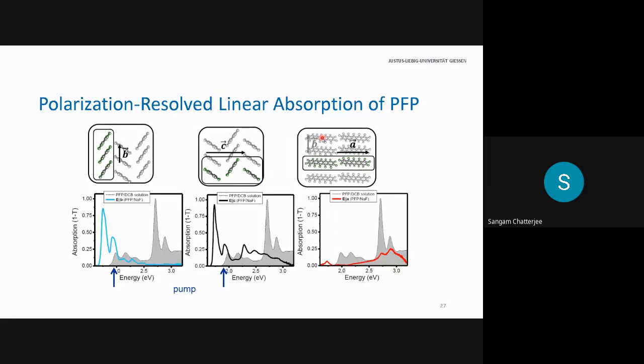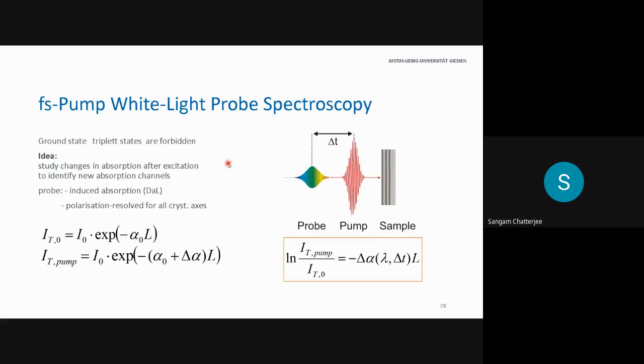And the linear absorption spectra for the three directions are shown here. And you see drastic changes in the A direction, where you have this head-to-tail arrangement, compared to the C direction and the B direction. And there are more subtle changes in the B and C direction, which are a direct consequence of the Davydov splitting at the low energy resonances. And there are more pronounced changes at the higher energy resonances, which is probably a consequence of H and J aggregates that form here, or you project out of the coupled system, but I'm not going to touch upon that.